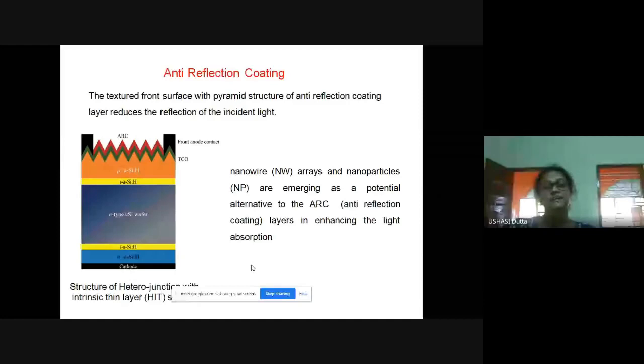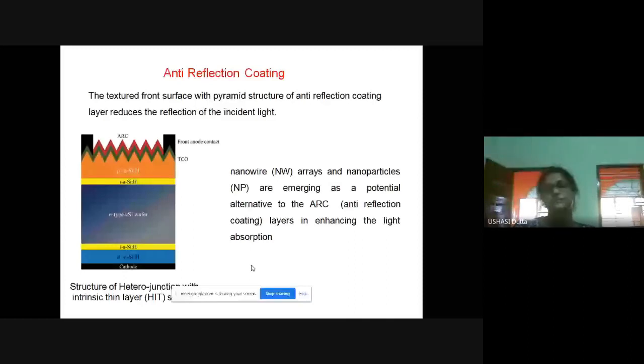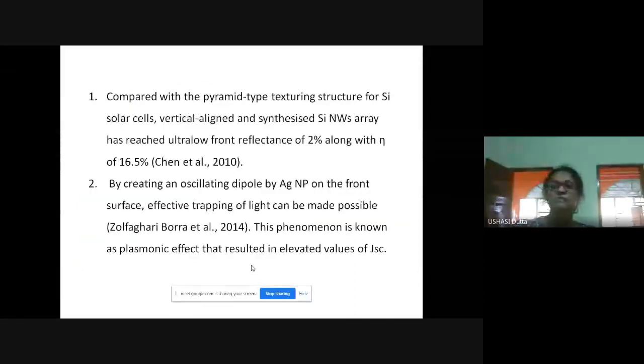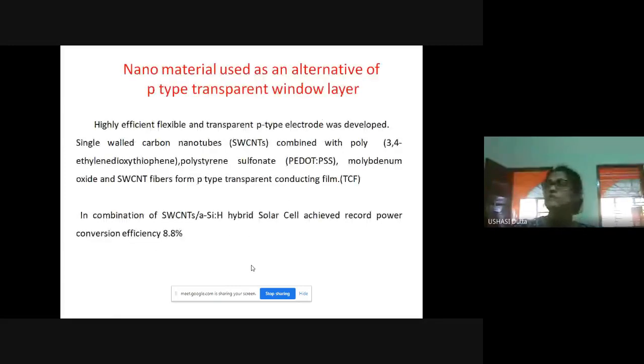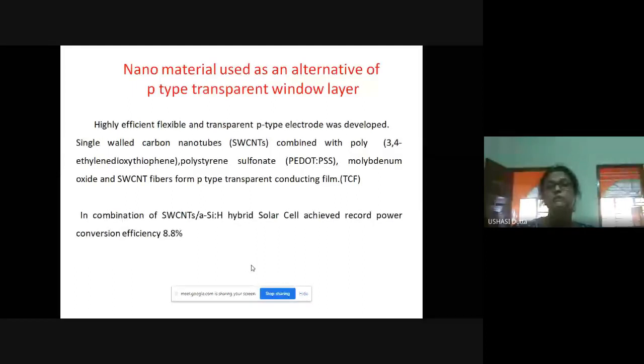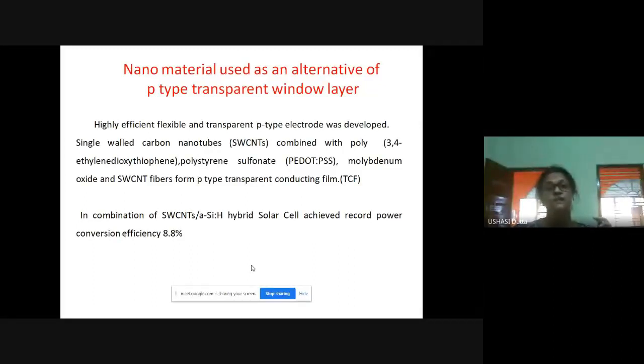And this is the structure of a heterojunction intrinsic thin layer, where ARC is used. Here ARC is the anti-reflection coating. The pyramidal structure of the ARC is replaced by nanowire arrays or nanoparticles that enhance light trapping and increase the current. This is the pyramid type textured silicon solar cell, done by Chen, which shows that the efficiency increases to 16.5%. And here we see that nanomaterial used as an alternative to the P-type transparent conducting window layer, in combination with single wall carbon nanotube and amorphous hydrogenated silicon solar cell, achieved a record power conversion efficiency of 8.8%.